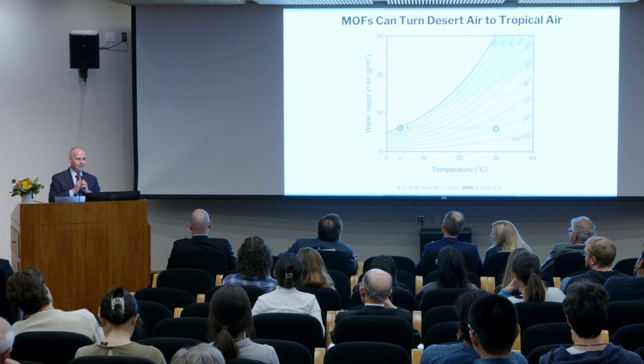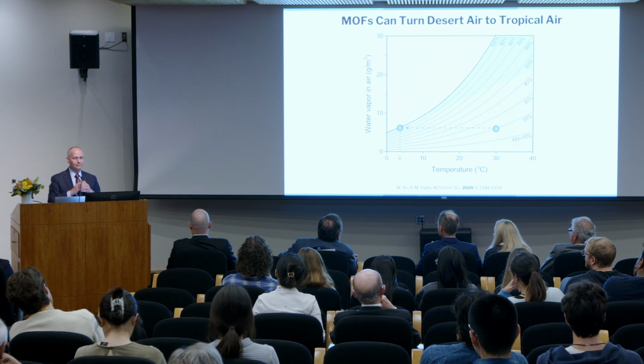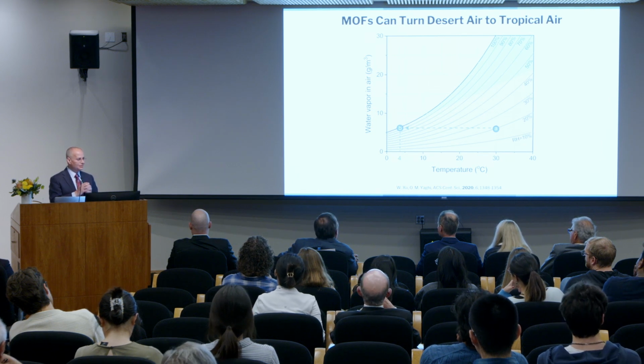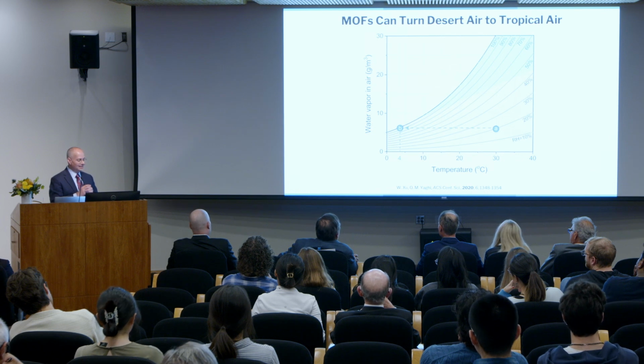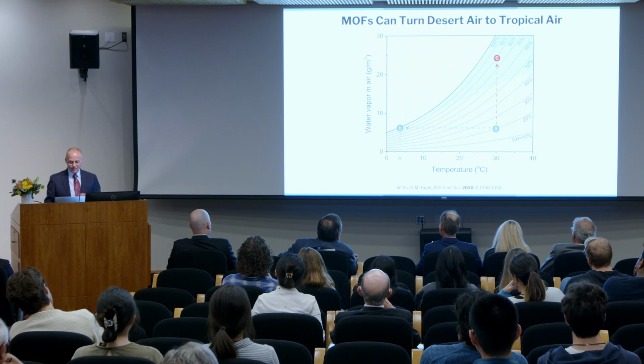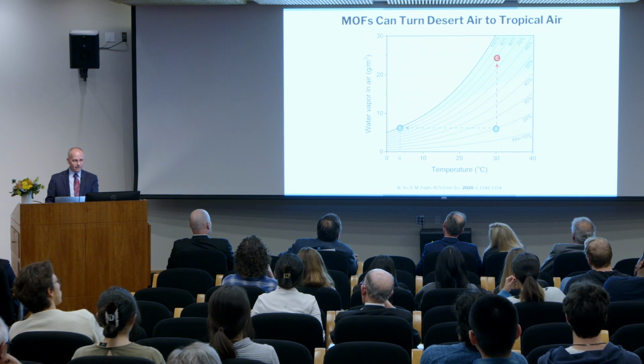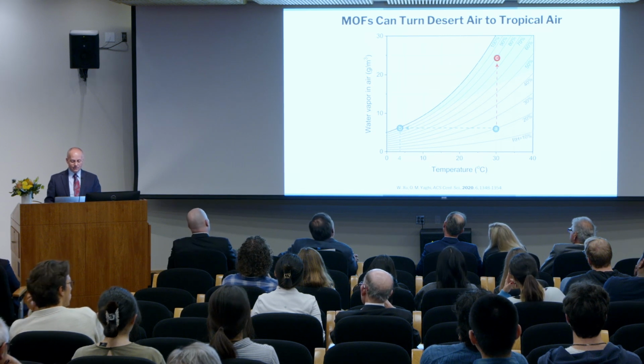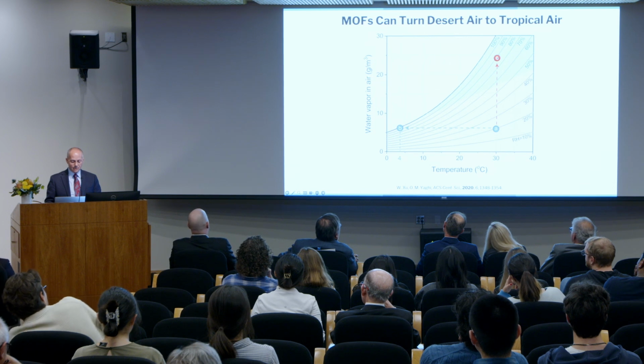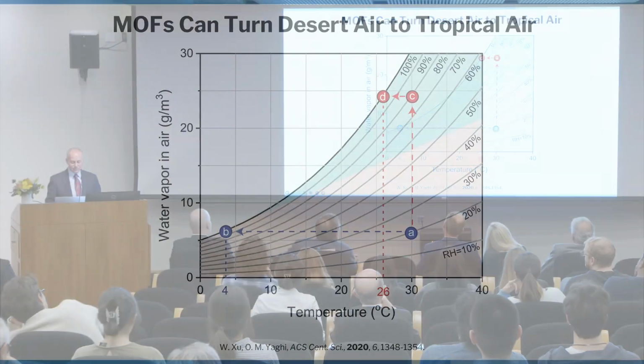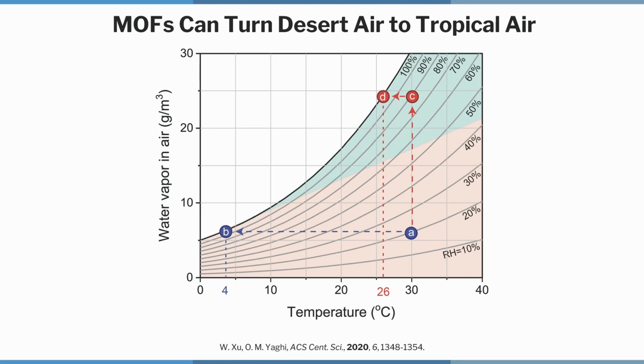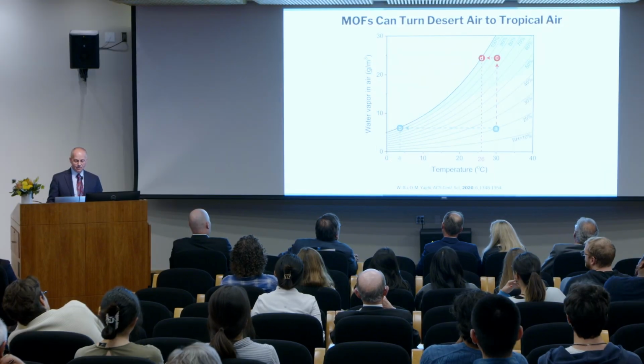I have managed in that experiment to turn desert air into tropical air. And therefore, now I have turned arid air with relative humidity of 20% to 80% or 90%. And to get the water out of that air, I only need to cool by a few degrees Celsius. Okay? That's the idea of water harvesting. That's how the MOF works.